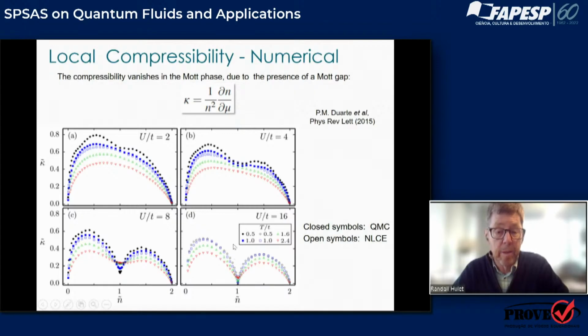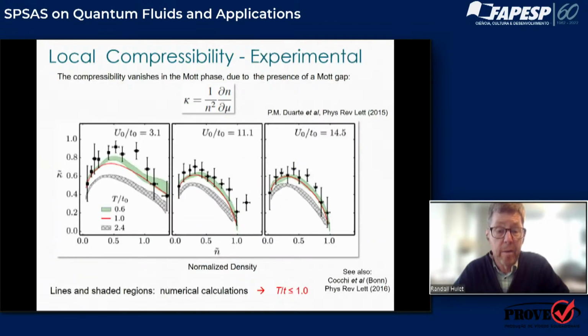And so if you could measure the compressibility by measuring the change in density with respect to numbers of atoms, you can compare directly with these calculations. So that's what we've done here. This is a paper whose first author was Pedro Duarte, experimentalist in my group. And the theory was, I think, done by Jason and Teresa. And you can see that as you go up in U, there is the first minimum, which is due to the fact that this is a Mott insulator, and the compressibility vanishes in the insulating state. And the comparisons are comparisons with theory.